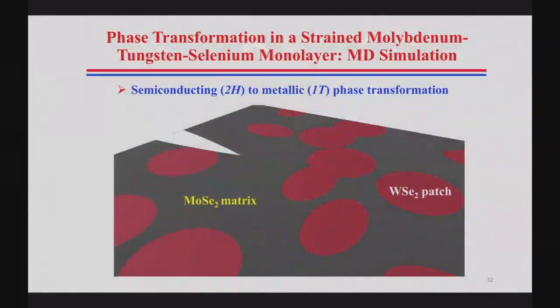So the modeling is this. We have one layer of molybdenum-selenium matrix, which is this black. Then there are these random patches of tungsten and selenium thrown in to mimic the experimental system. And we have a crack over here. I'll show you a movie of how the crack propagates in this.